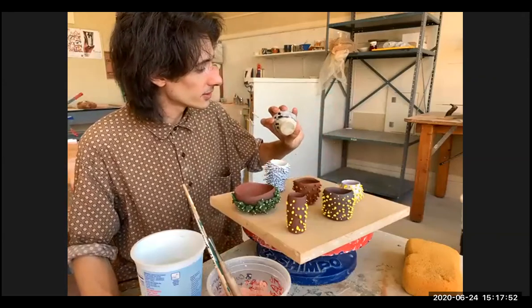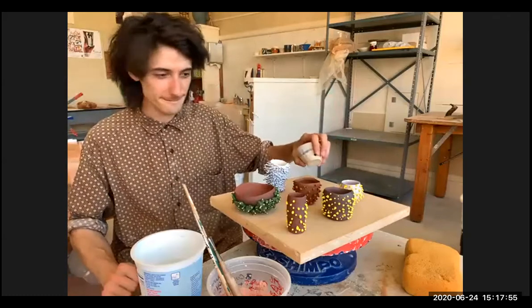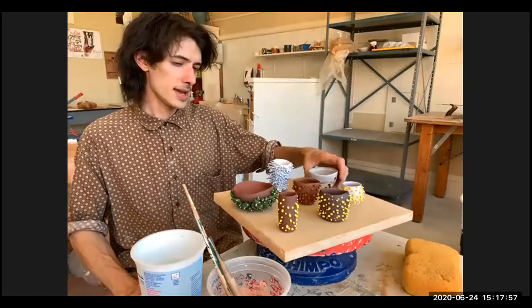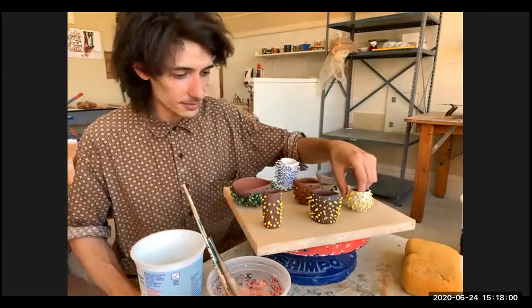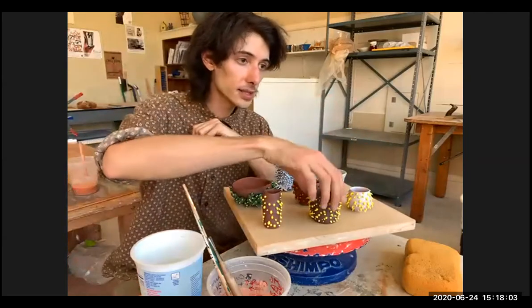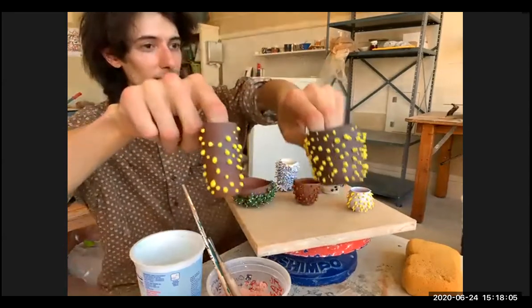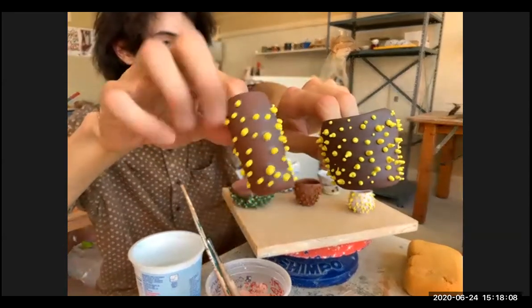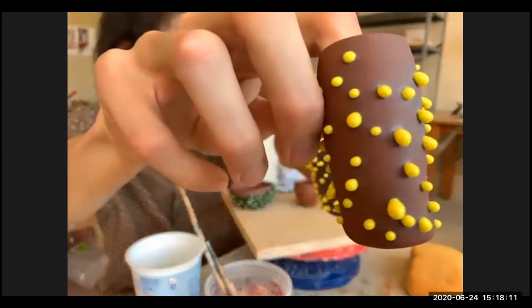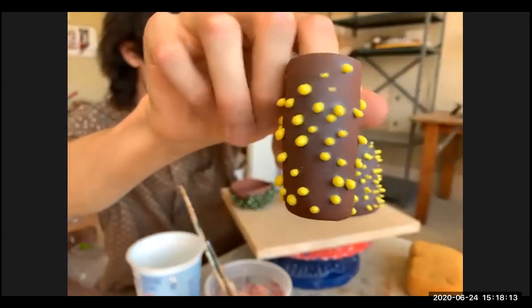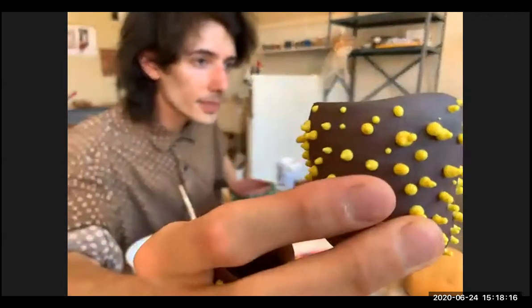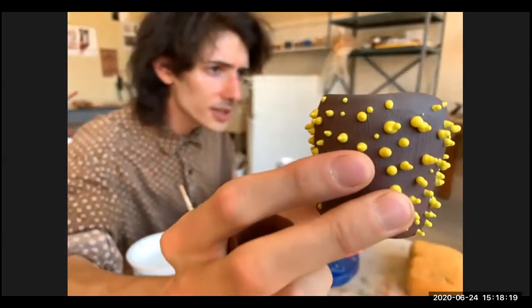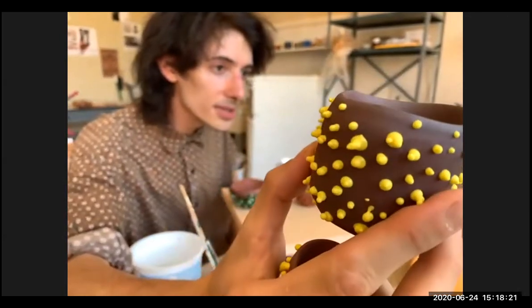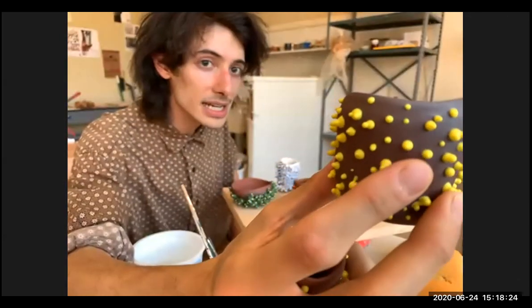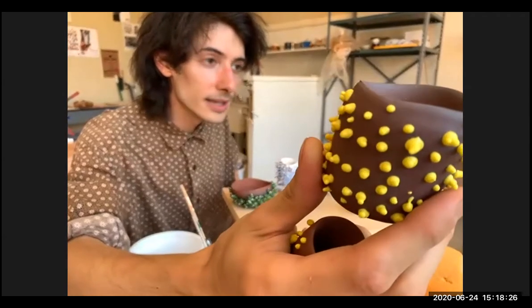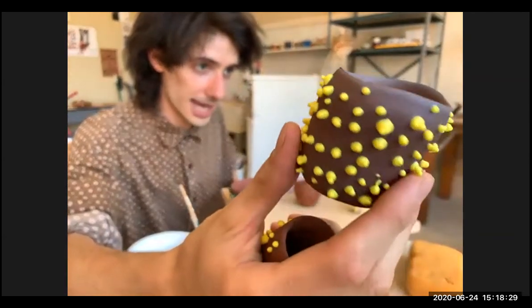Yeah, showing some interaction. Are all the yellow dots the same material? They are very slightly different recipes. These two, go and put a close up. So you can see this one, it's all droplets. They're quite round, and this one you can see there actually are nodules. So it's not melting as much. It's basically maintaining the same form that it goes into the kiln as.